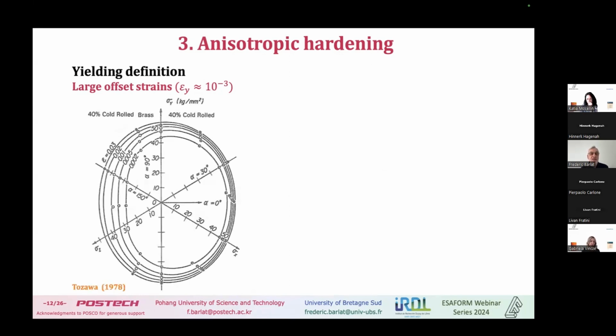It's about plane strain compression, biaxial compression, as I showed you before, with a stacked sheet specimen. And what happens in this example is that it's brass. The first step was rolling. It follows this purple curve here. Then unload, and then reloading in a different direction to probe the new yield surface. And this is done after different offset strains, like the first curve represented here at 2 times 10 to the minus 3.